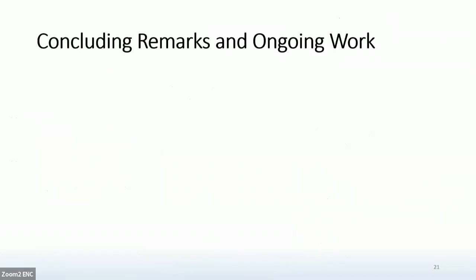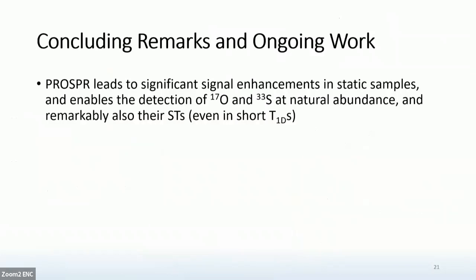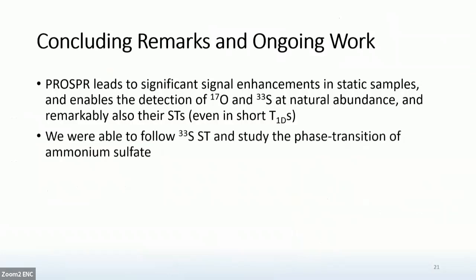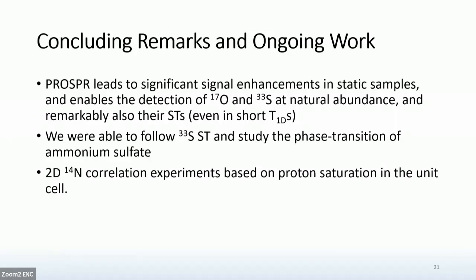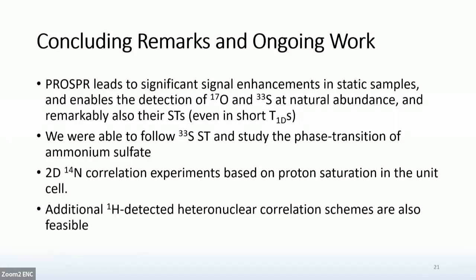So just to conclude, I showed you that PROSPR leads to significant signal enhancements in static samples and enables the detection of oxygen and sulfur at natural abundance. And remarkably, we were also able to measure the satellite transitions, even for short T1Ds. We were able to follow the sulfur satellite transitions and study the phase transition of ammonium sulfate from the sulfur point of view. And then I also showed you a 2D N14 correlation experiment based on the proton saturation in the unit cell, and this is still ongoing work.